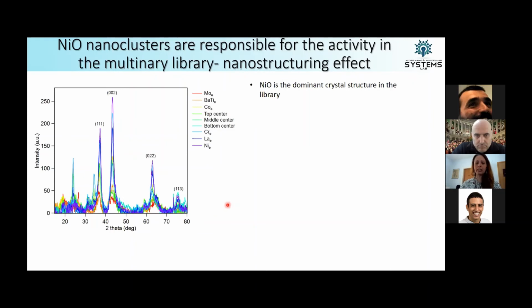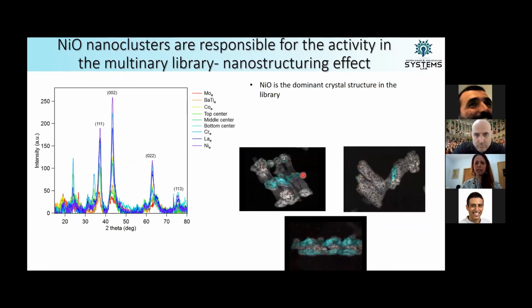So our theory is that the nickel oxide clusters become very dominant in the activity. And what we did also to further look at this is again re-examine the TEM images, and you can really see that the nickel oxide is situated in clusters within the different nanoshapes. So these nickel oxide clusters would not have formed had it not been for the nanoshapes. So they're really situated in tiny areas throughout these nanostructures and nanoshapes on the library. So these nickel clusters seem to be the dominant factor.